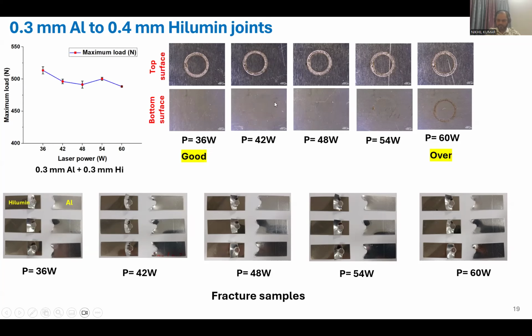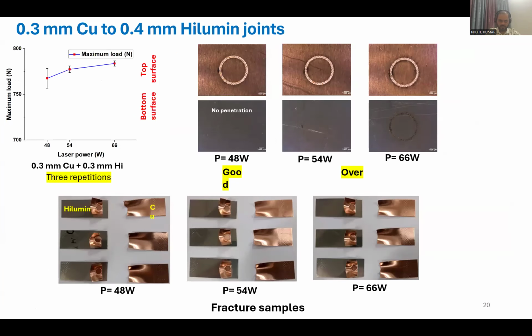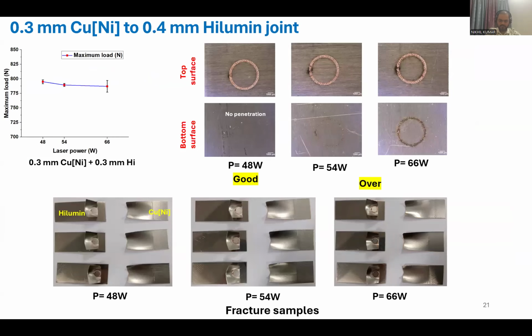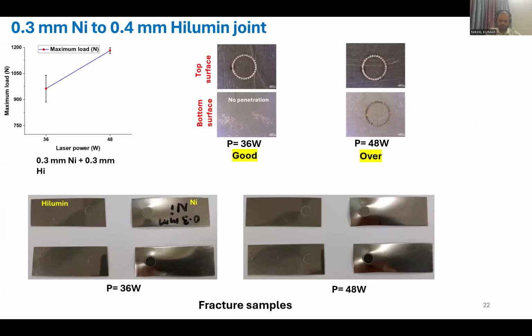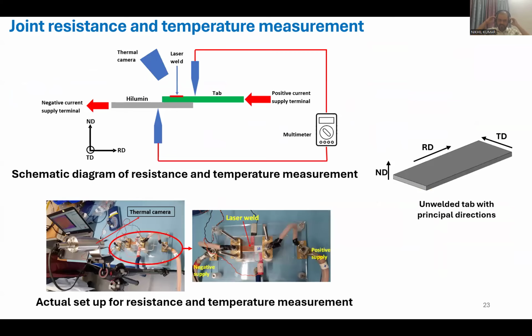And this is also a good parameter because here also we are not seeing any penetration. This is also a good parameter. This is overweld, these last two pictures. So this is for 0.3 to 0.4 and this is 0.3 to 0.4 copper. Same concept here for optimizing. This is for nickel plated copper. This is for nickel.